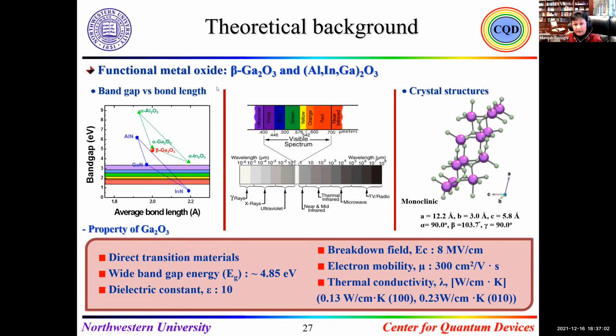For the functional metal oxide gallium oxide, if you look here, you have band gap as a function of average bond length. You know aluminum nitride, gallium nitride, indium nitride, but without any lattice matched substrate, you use sapphire. But if we come to gallium oxide, you have aluminum oxide with much higher energy gap, alpha gallium oxide, beta gallium oxide, and indium oxide. So by doing band gap engineering the same way we did for aluminum nitride and gallium nitride, we have much better area to make useful optoelectronic devices.